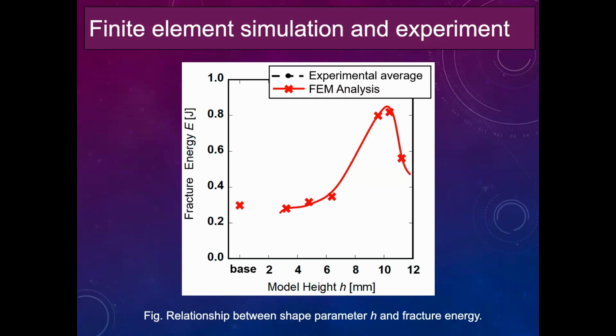This is ideal data for us, and this is very comfortable for us. But when we also plot the experimental data on the same graph, as shown here, this dotted line shows the experimental data. You can see from this graph that there is a little bit of difference between the experiments and the FEM results in the fracture energy values.